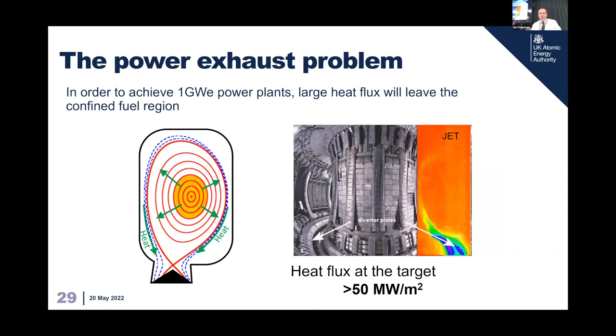Now, we don't just let it go out and hit the wall. We use magnets to sweep it down to a sacrificial surface at the bottom, and that's a consumable. So that will melt over time and you just have to replace it every few years. And you can see that in the IR, the infrared image of JET here, where all the heat is going down at the bottom here. Now, in a power plant, the heat down at the target here could be sort of 50 megawatts a square meter. For context, that's like an arc welder, right? So it's really, really high heat flux, certainly well above a re-entrant space shuttle, things that are designed to melt the blade. So it's a really, really challenging heat exhaust problem.